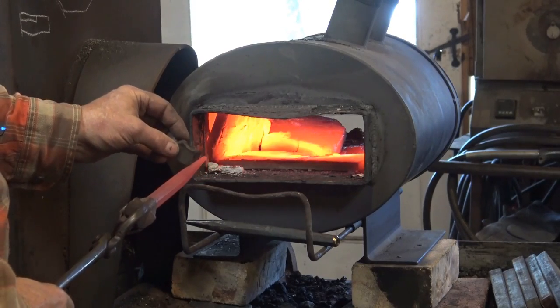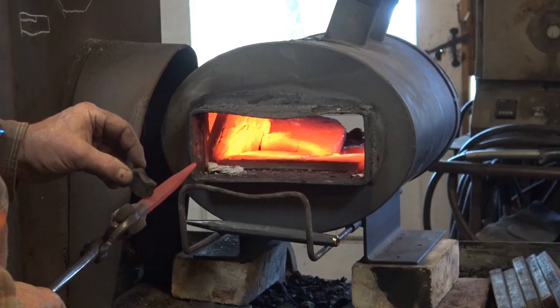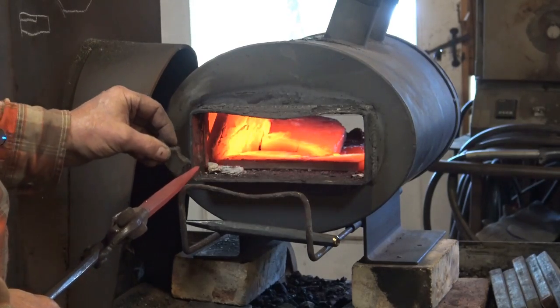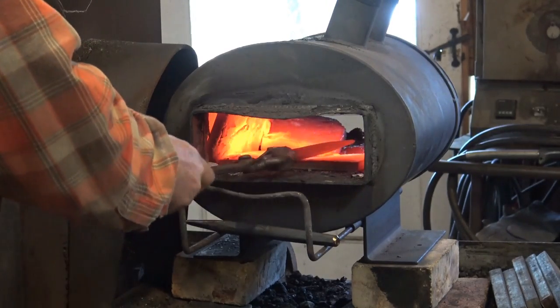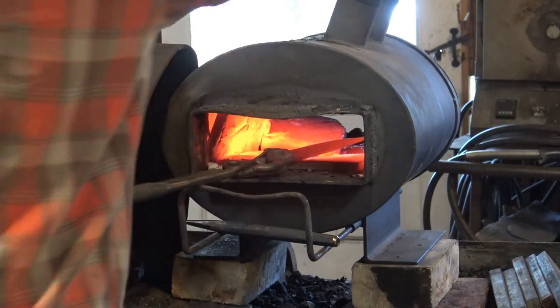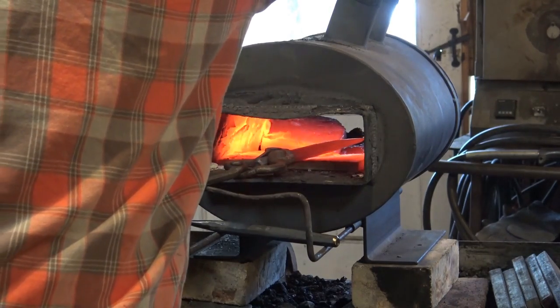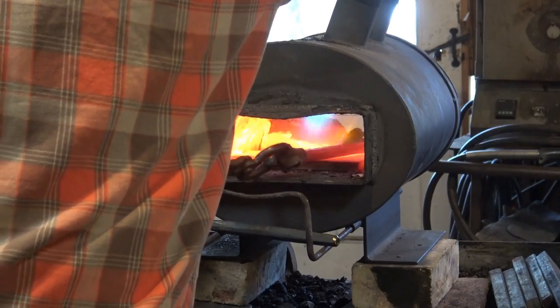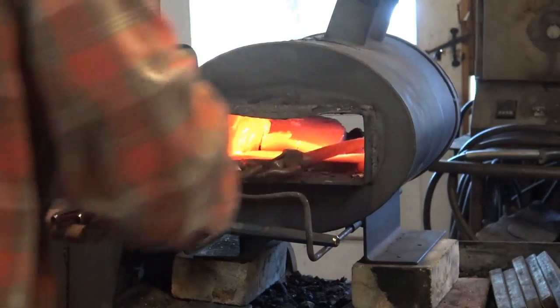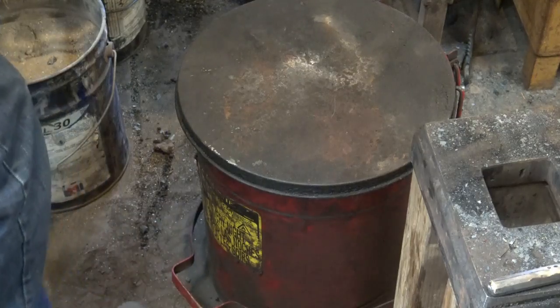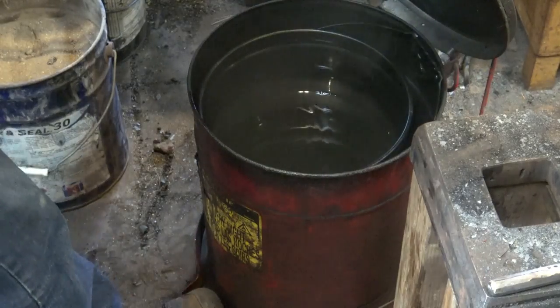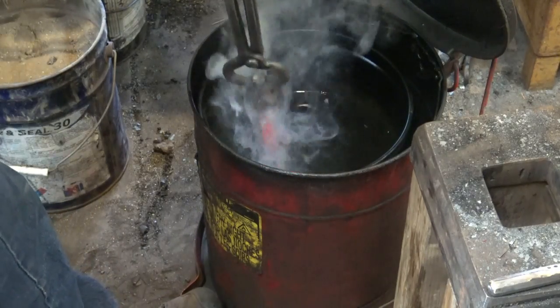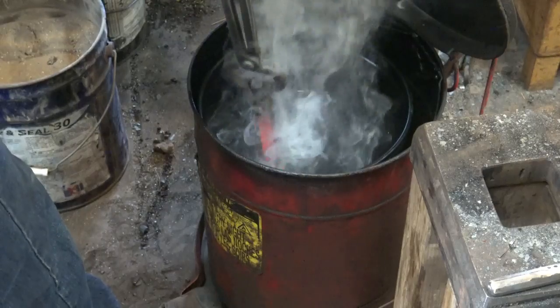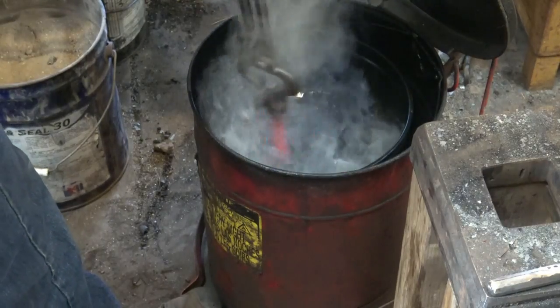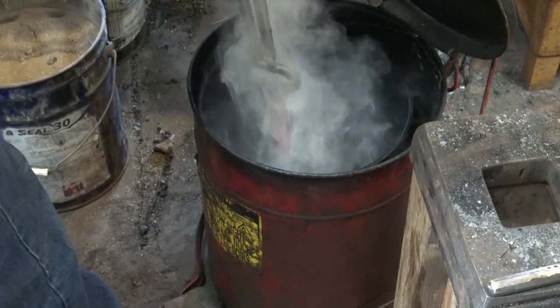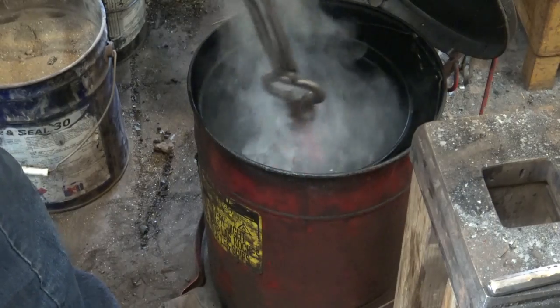Now that edge is good, that it's non-magnetic. It's magnetic back here. So we're pretty much right where we want. Make sure you quench on a rising heat. We're going to quench in our preheated oil. We're going to do about the last inch or so. That's really all that matters. Nothing else is ever going to be used as a hot work tool.